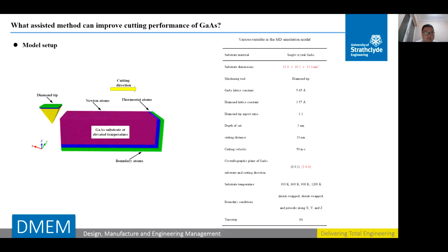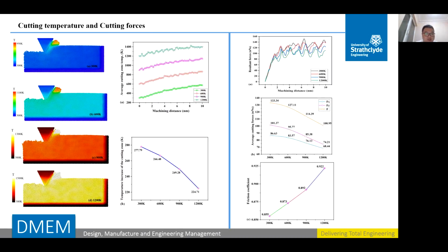On this page, I established the hot machining of gallium arsenide MD simulation model. Next, I chose three representative temperatures, 600 Kelvin, 900 Kelvin, and 1200 Kelvin, to cut gallium arsenide to benchmark against the cutting performance at 300 Kelvin, meaning room temperature. Hot machining results in reduction of cutting forces with increasing temperature. However, very interestingly, the coefficient of friction increased with increasing temperature.